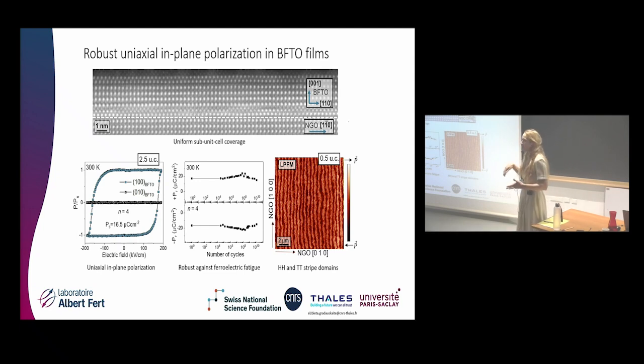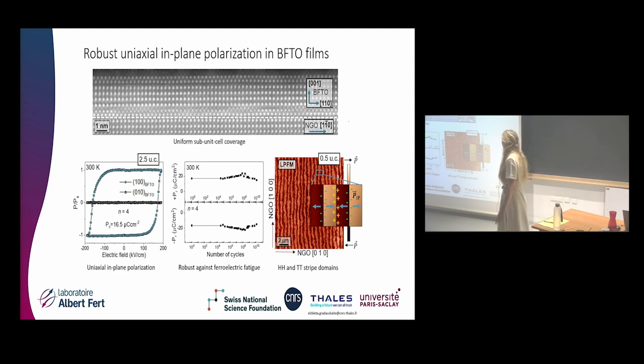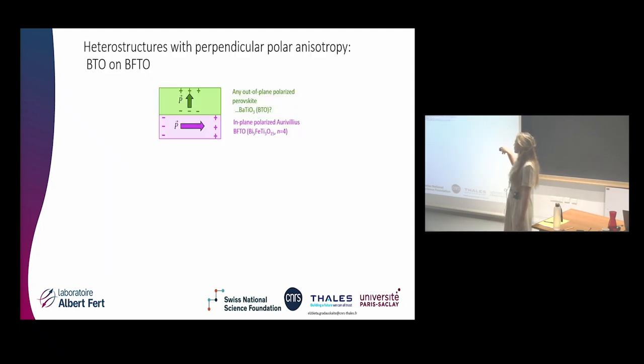Because now, of course, our polarization is in the plane, so it's no longer limited in the same way by the thickness, but it's more limited by the domain width. So our in-plane ferroelectrics, even at half a unit cell, already have polarization. And what's interesting is that we have these striped domains where we have head-to-head and tail-to-tail domain walls in the films. Right, so now we have our first component here. We have a film that's very thin and has in-plane polarization. Now let's try growing something on top, like barium titanate, that we know is out-of-plane polarized. And then, let's see what happens at the interface. Can we actually help to stabilize the polarization in this guy?